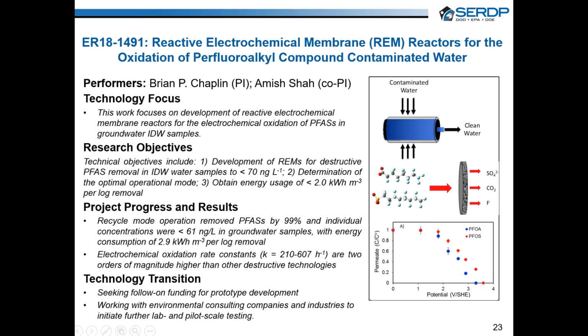A specific focus on treatment of PFOS and PFOA was made, which allowed comparison of results to existing literature. The oxidation of PFOA and PFOS in synthetic solutions indicated that approximately 5 log removal of PFOA and PFOS was achieved in a single pass through the reactive electrochemical membrane, with a hydraulic residence time of only 11 seconds and at applied potentials of 3.3 volts versus the standard hydrogen electrode for PFOA and 3.6 volts versus the standard hydrogen electrode for PFOS. Permeate concentrations were below the analytical detection limits of 86 nanograms per liter for PFOA and 35 nanograms per liter for PFOS from initial concentrations on the order of 5 milligrams per liter.